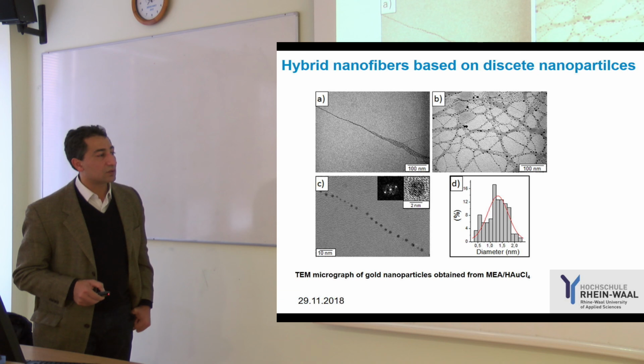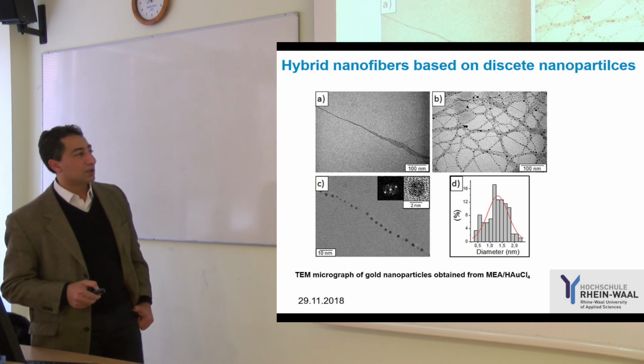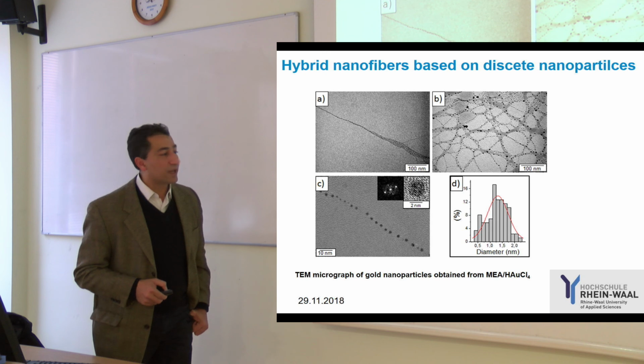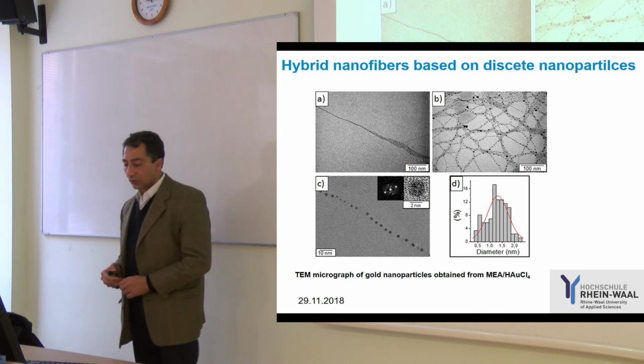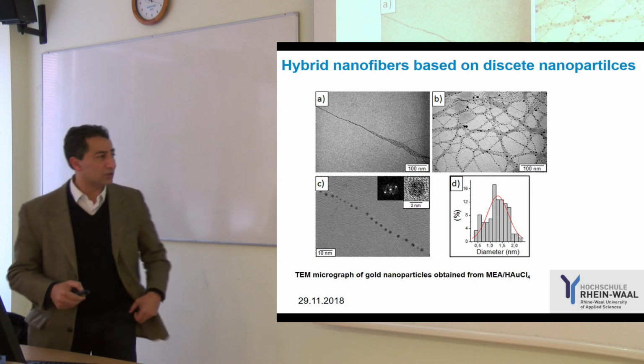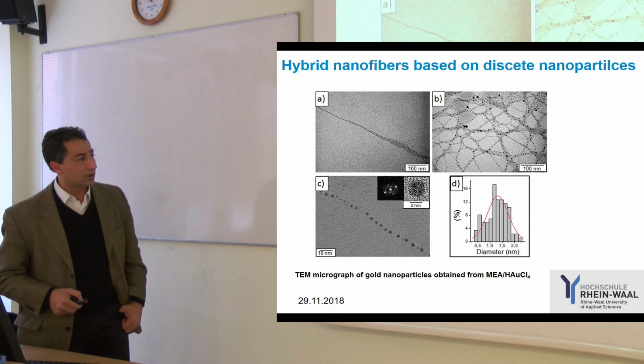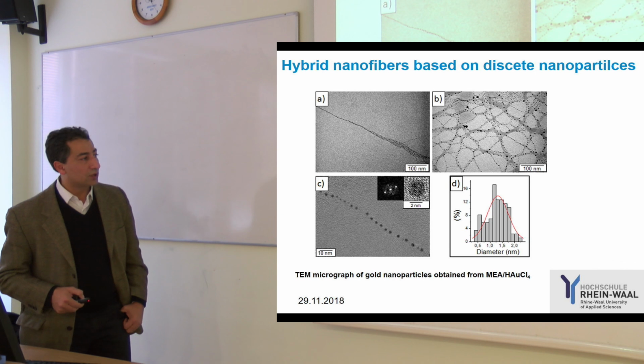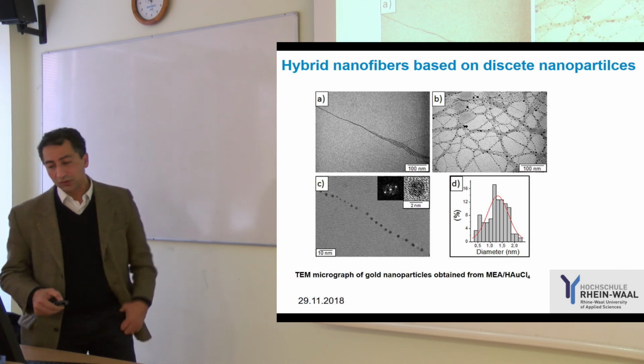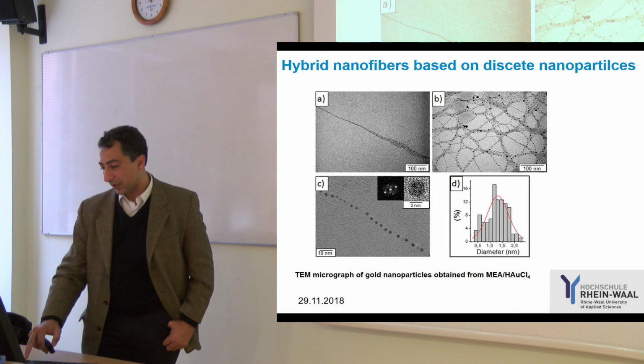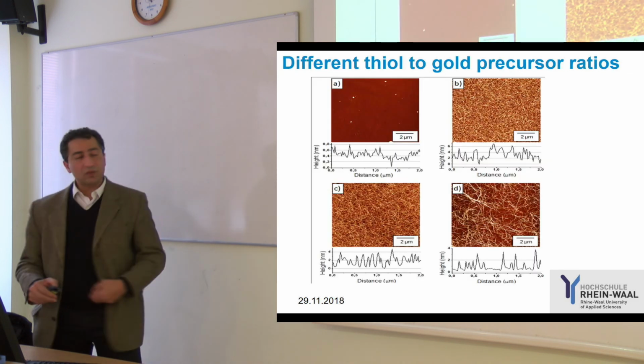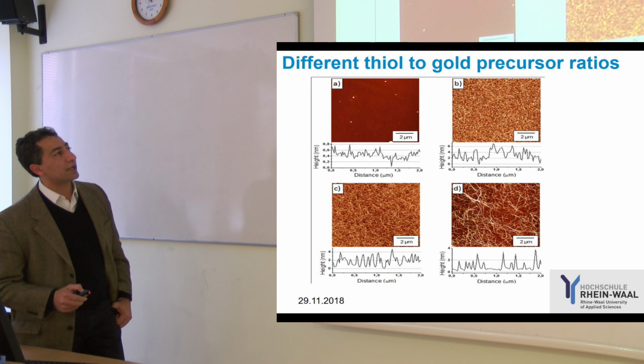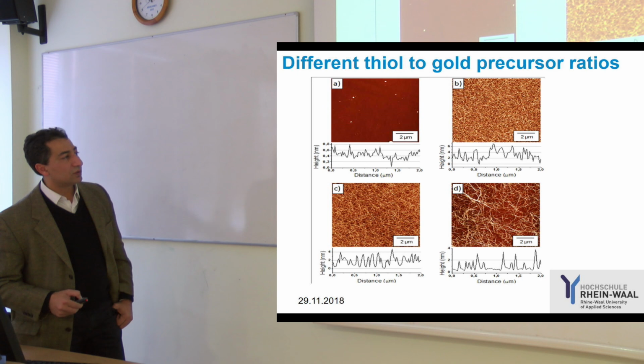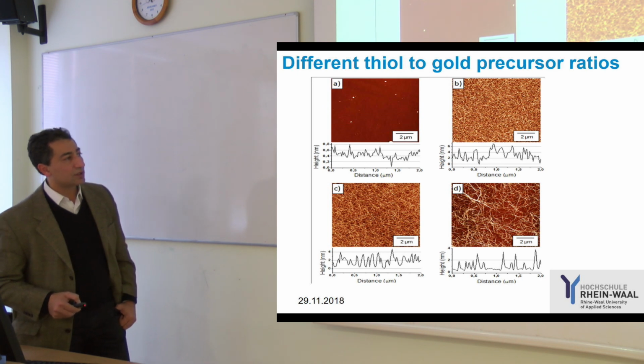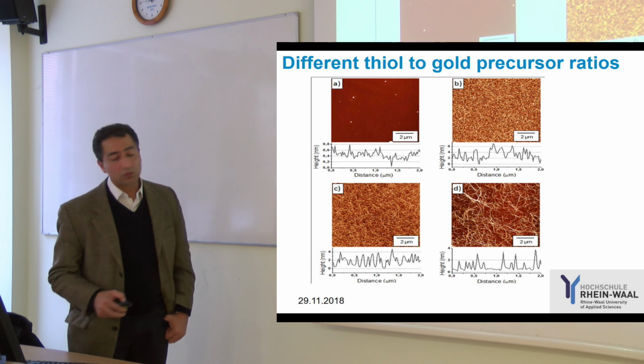We have very nice histograms that show the diameter of these particles is well controlled, and you can see we can use this in photonics or optoelectronics, where you can control the unique plasmonic properties of gold. You can see the distance is well controlled, so you can control the electric properties behind it. We use different ratios of precursor, our inorganic, so that we can move from particles to different levels of diameter of the 1D structure, and in the fiber here, this is in a well-controlled manner.